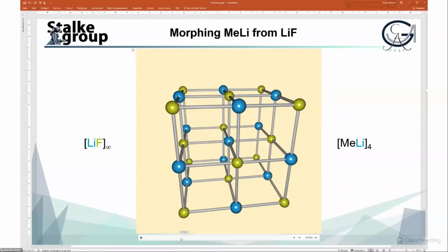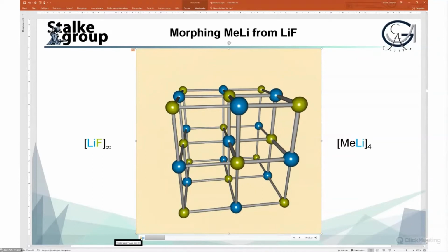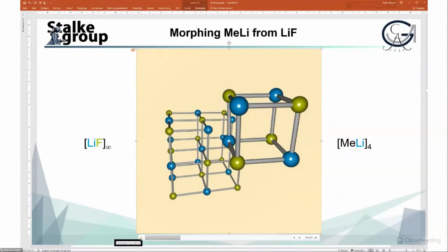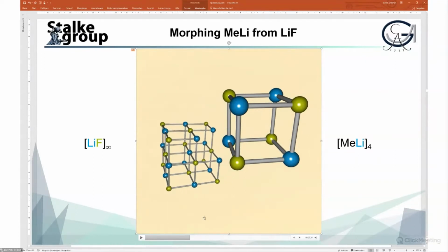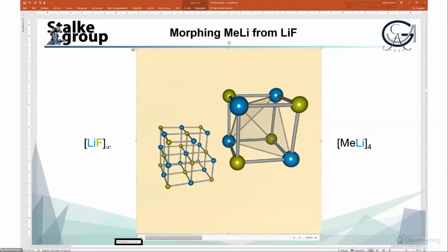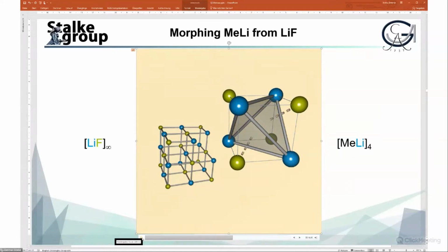Is this qualitatively different bonding? The answer is no, it isn't. If you take the rock salt structure and take out one unit cell, just one cell with 4 metals and 4 halides, which is an AB lattice, and then we connect the lithium atoms, give up the halide-metal interactions, and connect that to the face of the tetrahedron.